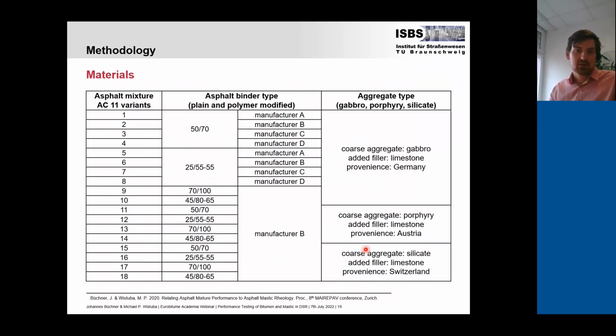The methodology here was that we looked at 18 different asphalt mixture AC11 variants, which were produced in our lab. We varied the asphalt binder type, included 4 different types and 4 different manufacturers, as you can see here in the middle. We also varied the aggregate type. Since this was the German, Austria, Switzerland cooperation project, we used some aggregates from Germany, from Austria, and from Switzerland to compare the behavior of these different aggregates here.